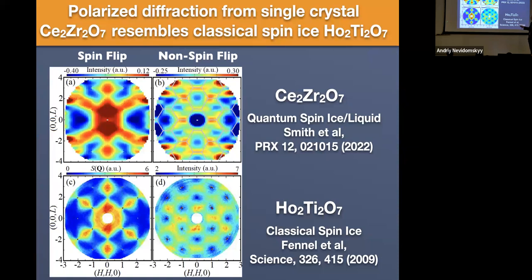Okay. And actually, one of the interesting things about doing this sort of measurement, first of all, it's integrating over all energies. And secondly, we can compare it to what's known to happen in a system where there's almost no disagreement that this is a classical spin ice, and this is holmium titanate. And this is a very famous paper, published about 14 years ago, showing the same measurements for classical spin ices. And you can see the similarities and differences, but they're pretty significant.